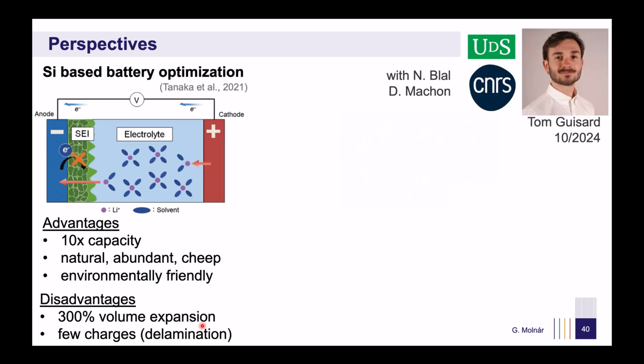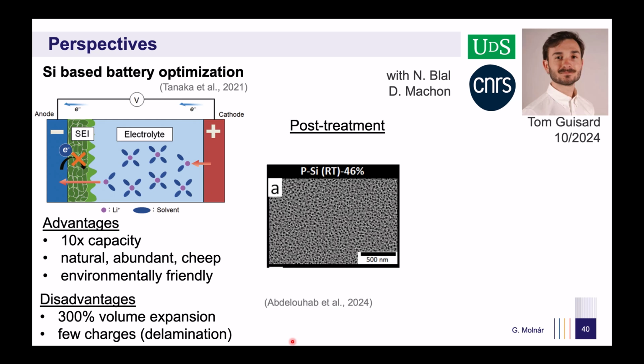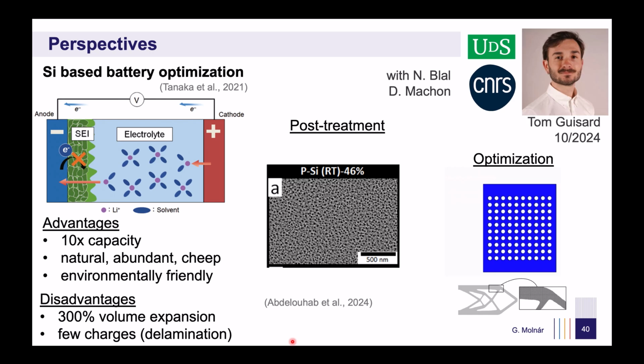Finally, at the metamaterial level, Tom's PhD focuses on optimizing the microstructures of silicon-based anodes. While these materials offer a capacity 10 times higher than their graphite counterparts, they are highly prone to fracture under repeated charging and discharging cycles. To address this, colleagues at Sherbrooke University have developed porous metamaterials designed to accommodate the significant volume change. Tom's work focuses on optimizing these material architectures using the phase field model to enhance their durability and performance.